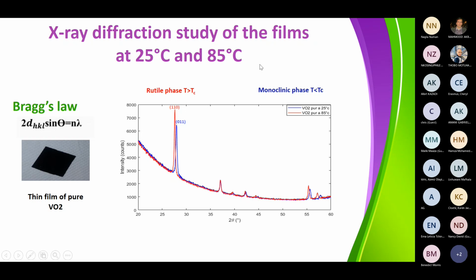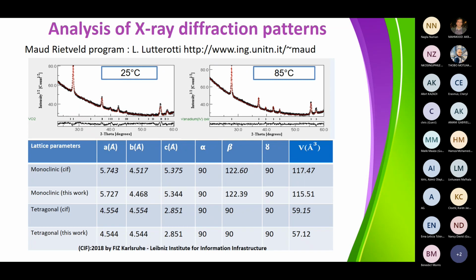And so then you would say, okay, fine, we see some differences. Fine, we know that there is a transition. Can we do it a bit better? Yes, we can do it a bit better by doing the analysis of the diffraction diagrams using a program. So last time I was here, I was introducing this type of material analysis technique, the Rietveld analysis. And that's what we were doing here. And you can see that at 25 degrees, we can calculate completely the full 2-theta pattern, diffraction pattern of the VO2. And we can do the same at 85 degrees Celsius. And in the end, we get information about the lattice parameters corresponding to the structure. So typically, you see, if you look at the literature, you will find CIF files for the monoclinic structure of VO2, and the same in the tetragonal phase.